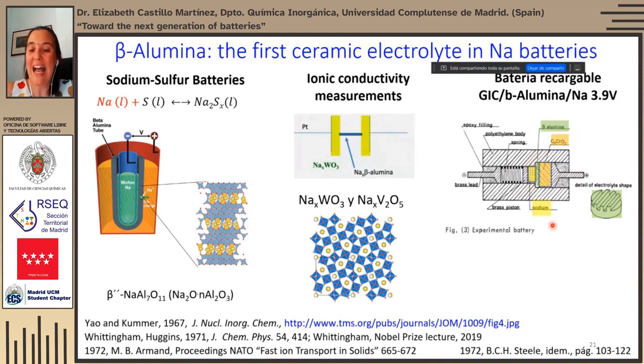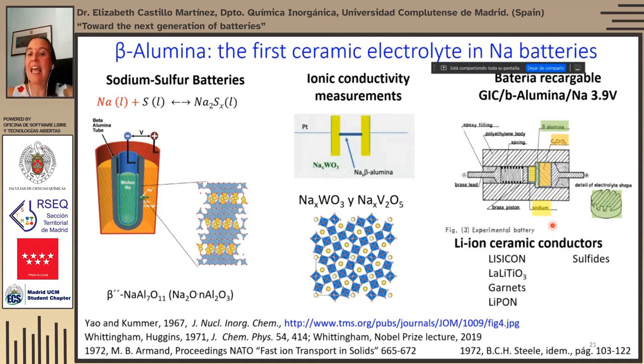And since these late 70s works, many lithium ion ceramic conductors have been proposed, mostly focused on lithium once the lithium ion battery took off. These are based on the LISICON lithium superionic conductor structure, the perovskite lanthanum lithium titanate, as well as the garnets, or the amorphous LiPON glasses and sulfides.